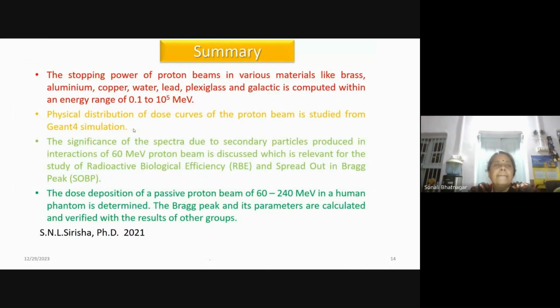this student. And the results for this work were that the stopping power of the proton beam in different materials like brass, aluminium, copper, water, lead, plexiglass was computed. And then the physical distribution of the dose curves was also observed. And these two parameters, relative biological effectiveness (RBE) and spread out Bragg peak, were also studied. And the details are all given in the published work, which is given in the paper also, the attached paper to the conference.